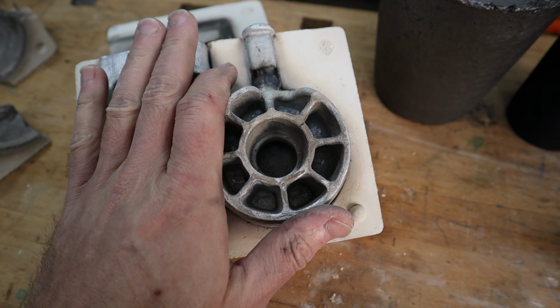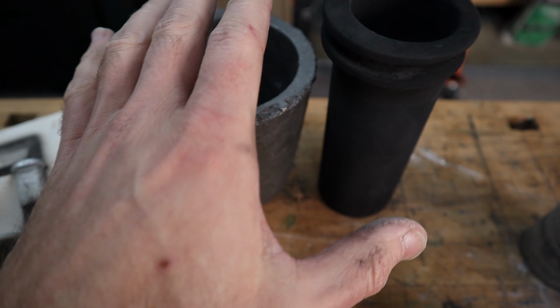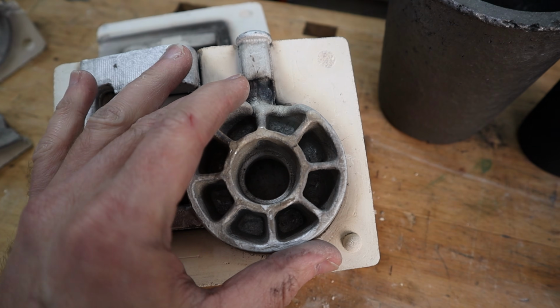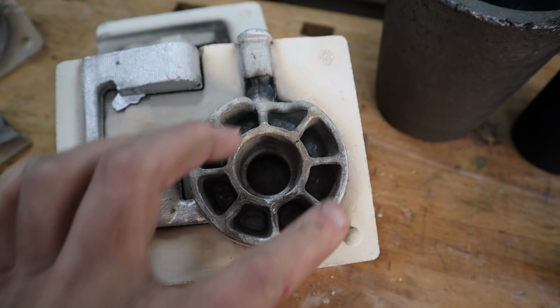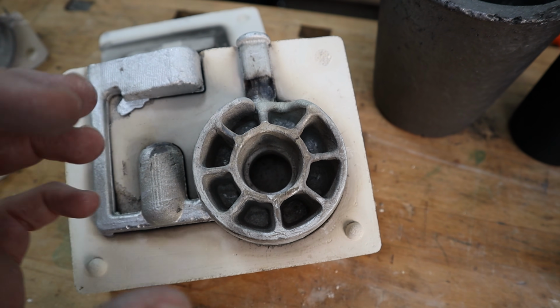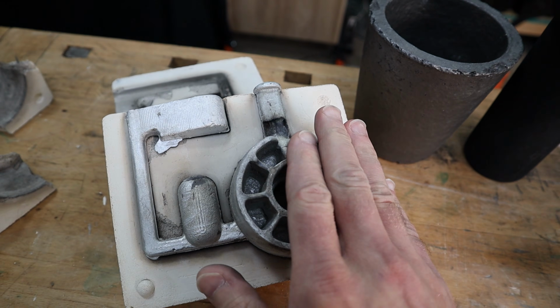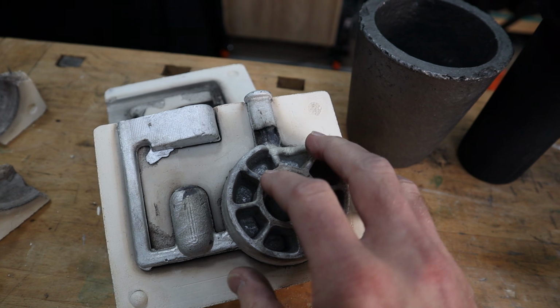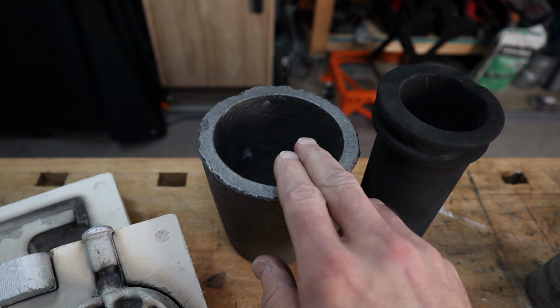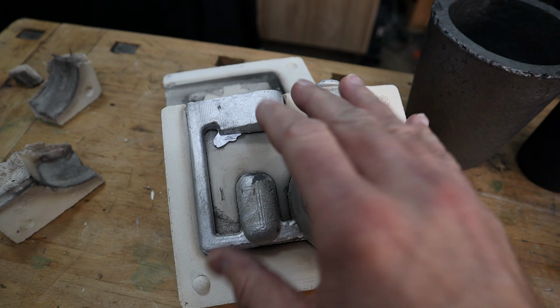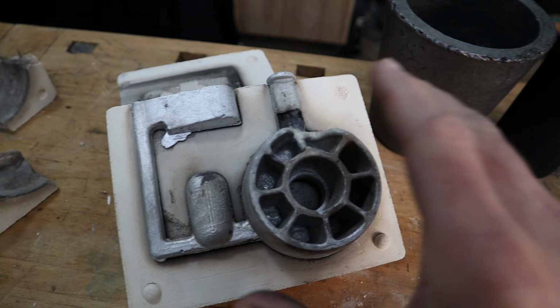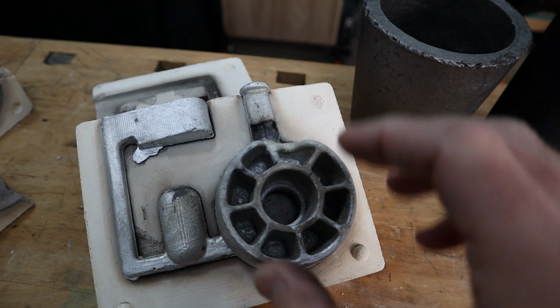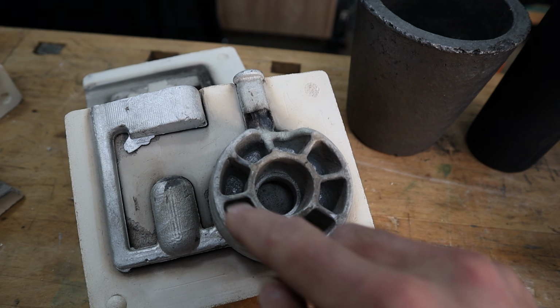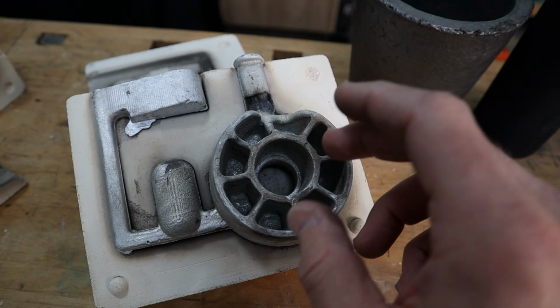So again, the failure in this one relates to the fact that I don't have enough material to pour a piece that's this big unless I do this ribbing, and with the ribbing it really just does not work very well. Now I could try and make this work, but I think the best solution really is to find a way to melt more metal, adjust the sizes of everything to be a little bit larger, and instead of having this ribbing in here, it's just going to be completely solid, and if I wanted to remove this later, I can do that at the CNC machine.